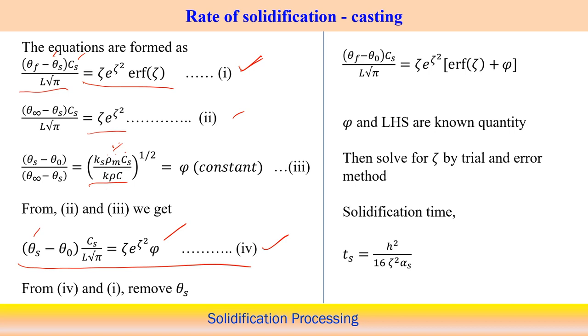So, from these two equations, if we try to remove theta s, then we reach this expression: (theta f minus theta 0) by L root pi C s equal to zeta e to the power zeta square error function zeta plus phi. Theta f and theta 0 are well defined, and theta s is some intermediate temperature, so in most cases theta s is unknown. That is why we eliminate theta s from these two expressions and reach an expression in terms of the other temperatures, because those are very clearly defined in this particular process problem.